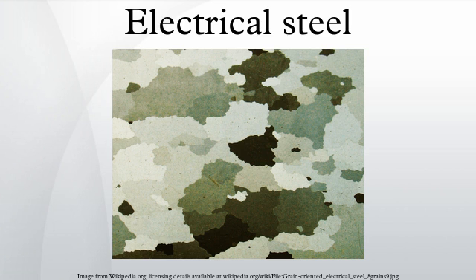The magnetic flux density is increased by 30% in the coil rolling direction, although its magnetic saturation is decreased by 5%. It is used for the cores of power and distribution transformers. Cold rolled grain-oriented steel is often abbreviated to CRGO. CRGO is usually supplied by the producing mills in coil form and has to be cut into laminations, which are then used to form a transformer core, which is an integral part of any transformer. Grain-oriented steel is used in large power and distribution transformers and in certain audio output transformers.